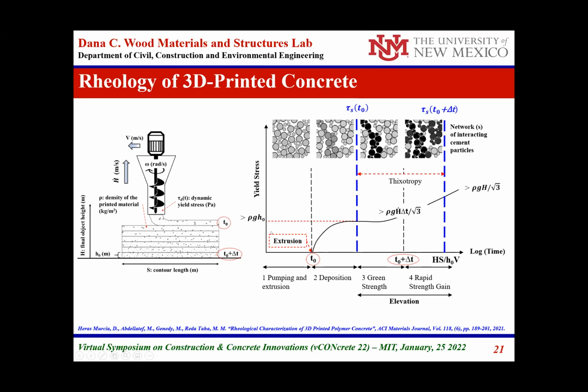What matters really is that at any moment, the yield strength of the material is higher than the tangential stress that is developed because of the gravity load of the top layers. You can see the different stages here related to pumping and extrusion of the material, deposition, the development of the green strength, and then that rapid strength gain related to the material being able to have enough shear strength in it to resist the stresses.